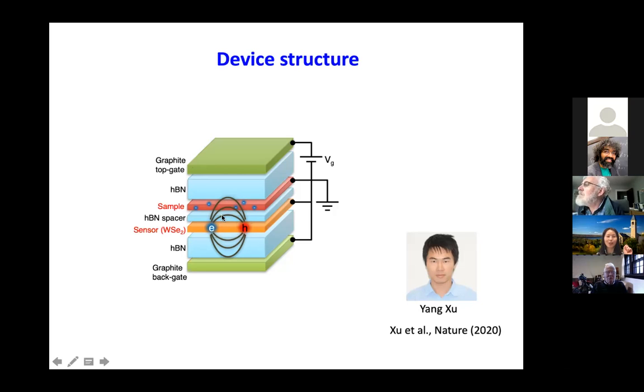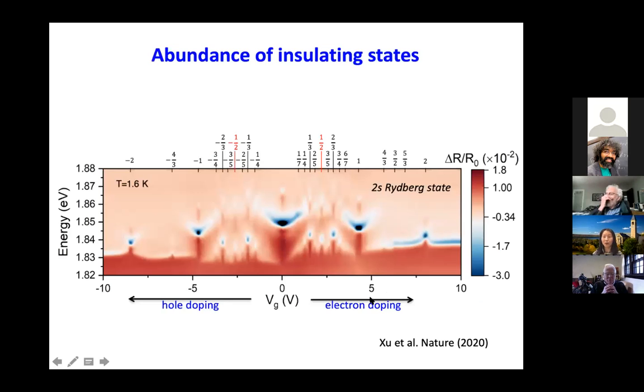Direct electronic interaction between the two is quenched by the spacer layer, because hBN, hexagonal boron nitride, is a very good insulator. But they can still talk, as I'm showing schematically here. Okay, and this is what we saw. What we are seeing here is the energy of that 2s state as a function of the average electron or hole density we loaded into the sample.